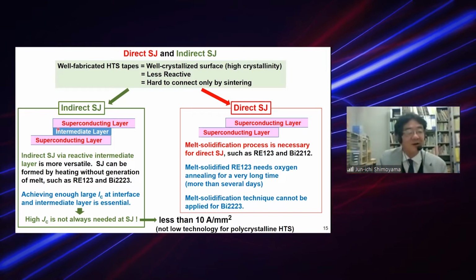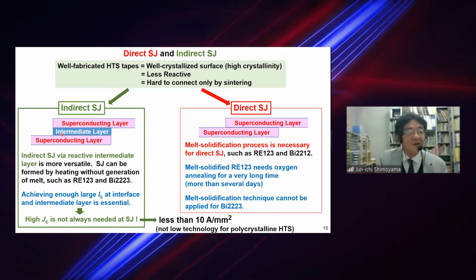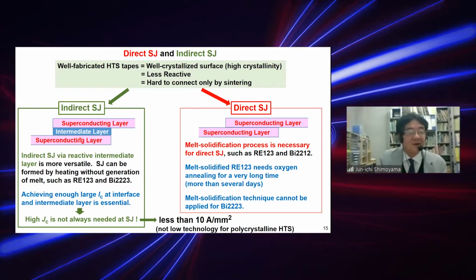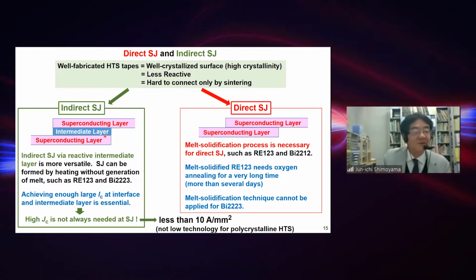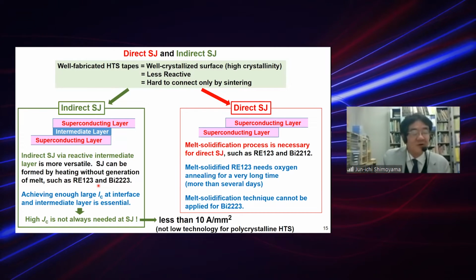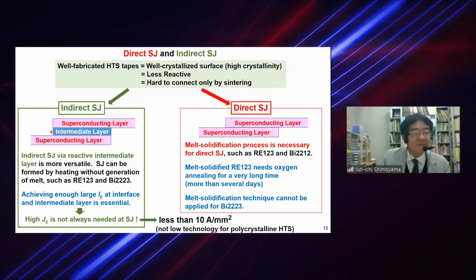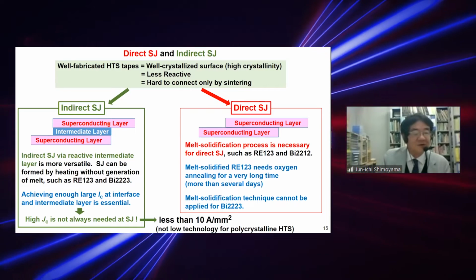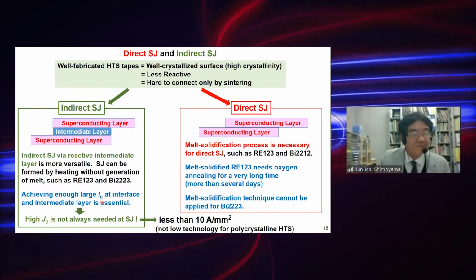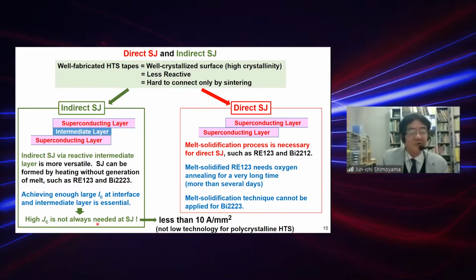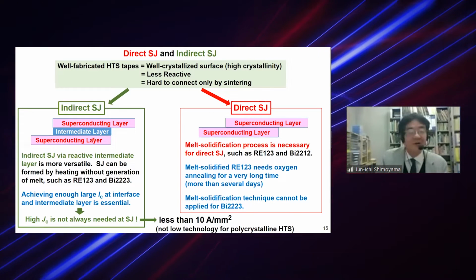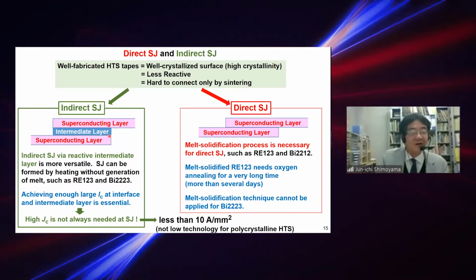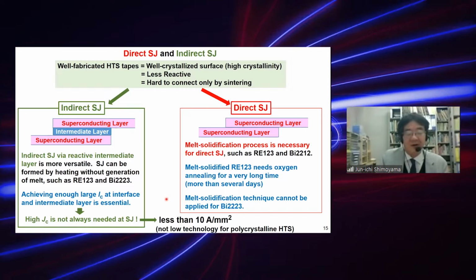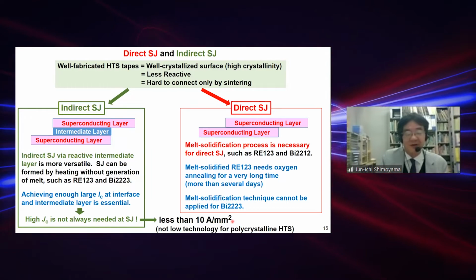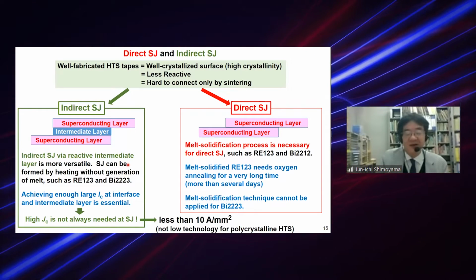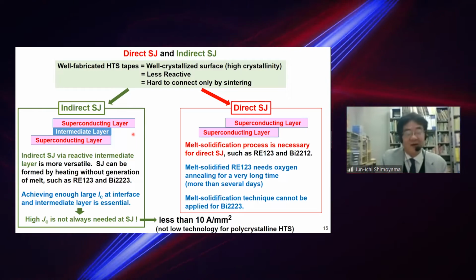However, the intermediate layer sometimes has a structure just like a sintered bulk. In this case, we must increase the JC of the intermediate layer connecting these two tapes. However, high JC is not always needed here because the contact area is very large. So therefore, less than 10 amps per square millimeter of JC is enough for intermediate layers.